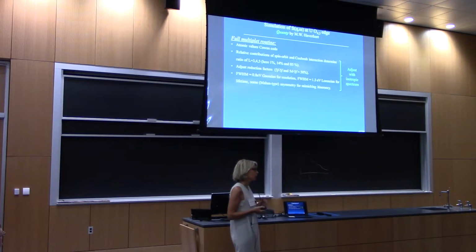And we have some line widths, Gaussian for resolution, some for lifetime effects, and some Mahan to mimic sort of the asymmetry. And we adjust this actually on the isotropic spectrum. The isotropic spectrum we measure by measuring many, many directions in the crystal. Because we are beyond dipole, it's not enough to measure 3 directions, we have to measure many.